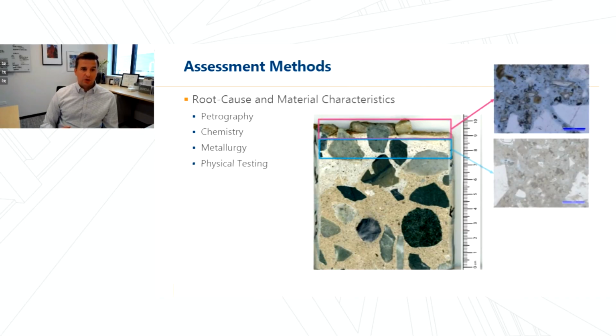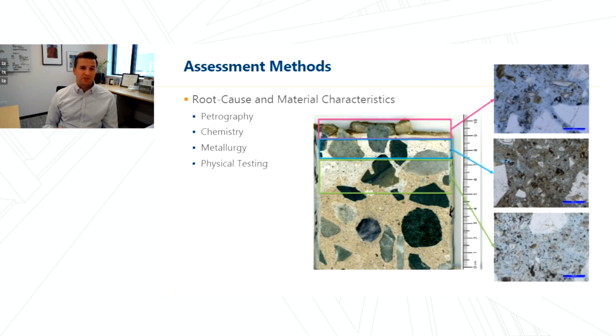So field methods do a really good job of identifying resulting damage and extent, but when we're assessing root cause, we're often aided and improved in our approach by material sampling and testing. This allows us to identify and quantify characteristics of the material. So I'm showing an example of petrography here. Petrography can tell us a lot about the original as-built concrete, changes in that concrete, and any remaining vulnerabilities in that concrete. I've mentioned analytical chemistry allows us to identify and quantify things like chloride and sulfate contents.